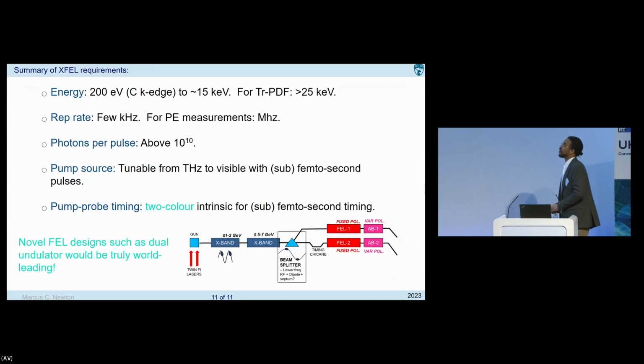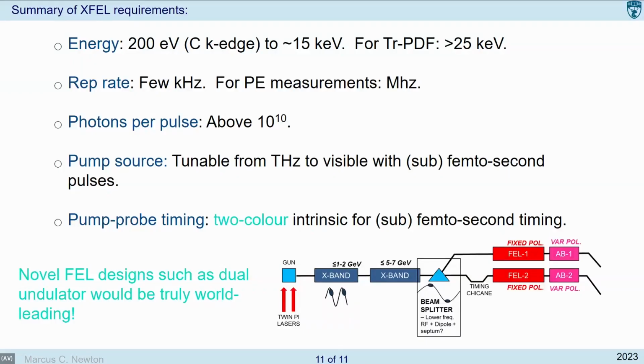Okay, so here's the summary of our requirements. We want energies from 200 eV, the carbon K edge, up to 15 keV, typically for most measurements. The time-resolved PDF measurements are slightly different, so the requirements are somewhat distinct, and we have to think about whether we want to incorporate that into our design of a FEL, or whether we want to internationalize and perhaps use another facility or buy into another facility to enable this technique, sorry, within our repertoire. So the rep rate, a few kilohertz typically.